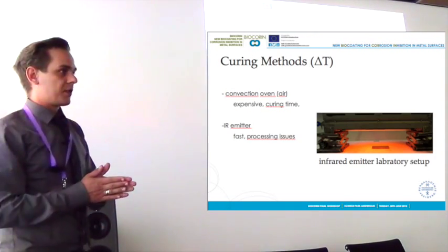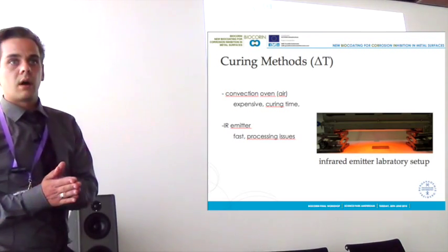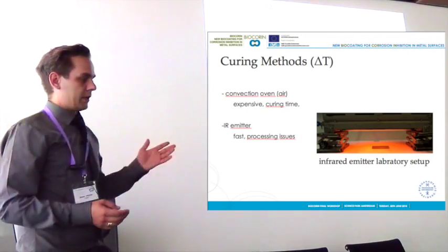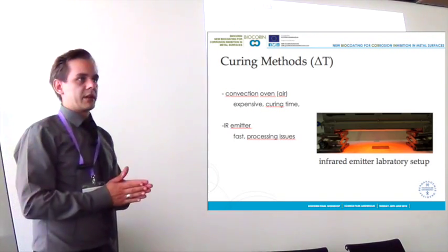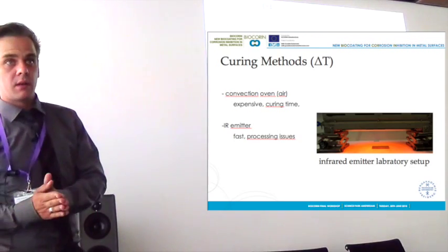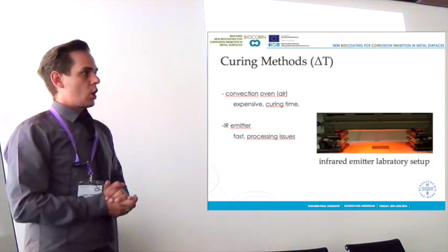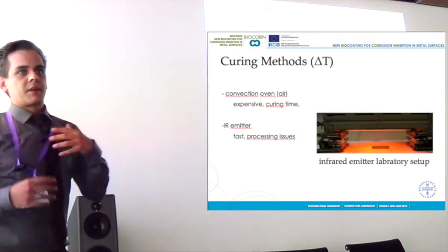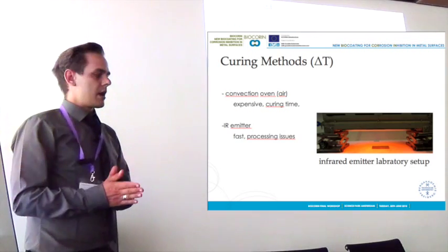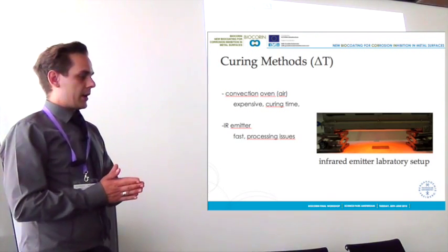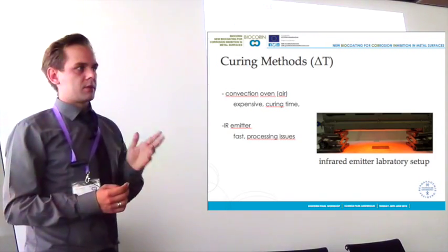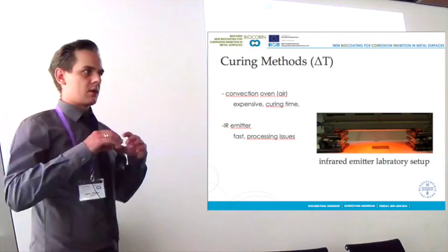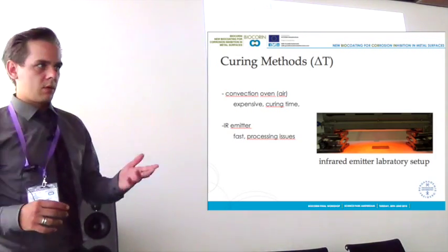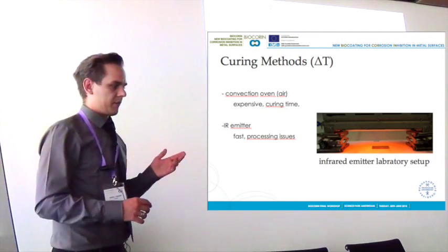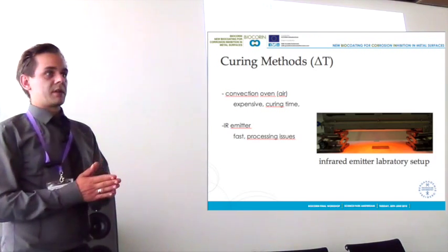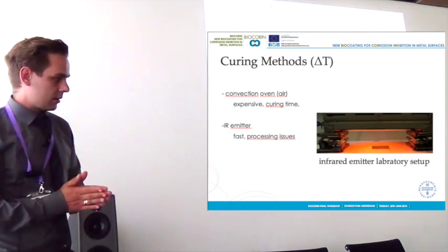Now I want to tell you something about methods that are useful to cure those materials. In sol gel chemistry, the most often used method is the convection oven in the laboratory scale, because you can investigate the curing behavior, what is the best temperature and time for the curing. But the big issue is when you go into the industry, it's very expensive, because if you change the shape of your product that you want to coat, you most often need a new oven, and it's very expensive. And the curing time sometimes takes very long.